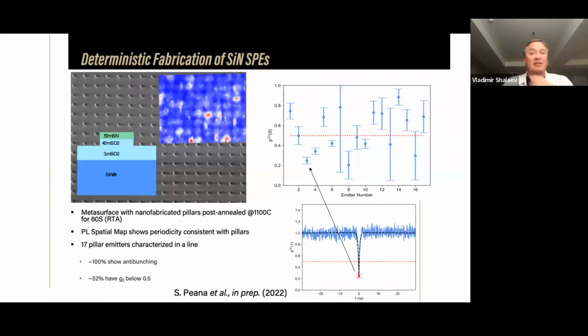This is an important slide in the following regard. It's the key thing if you're serious about photonic quantum computers: deterministically creating these single photon emitters. So what we tried to do, we fabricated many cylindrical pillars in silicon nitride, like is shown here. And it turns out that if you optimize the size of the pillar, then at a certain size most of the pillars actually have single photon emitters. That's all very recent results.